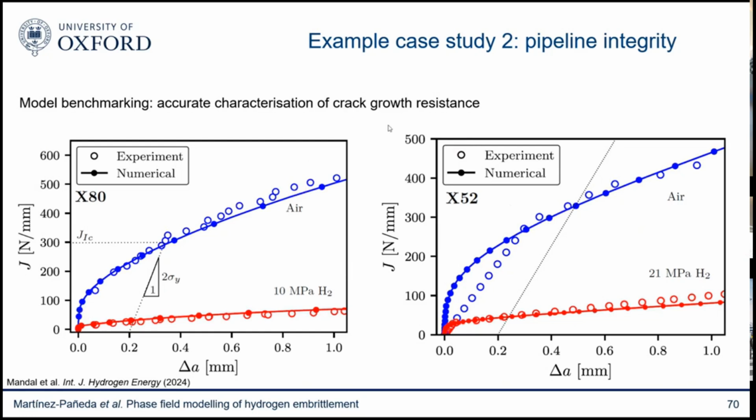We are quite confident that the model is able to capture very well how embrittlement affects these materials, what degree of plastic dissipation. So this is basically a model that is in agreement with well-established fracture mechanics, but it's also able to model hydrogen transport. It's also able to model a situation where you don't have a homogeneous material.